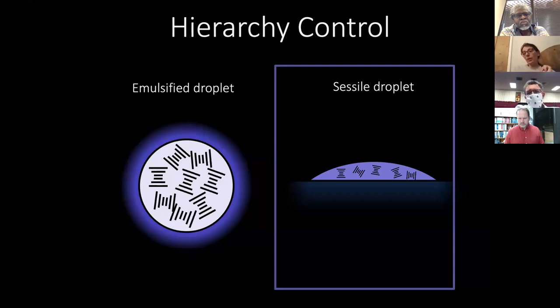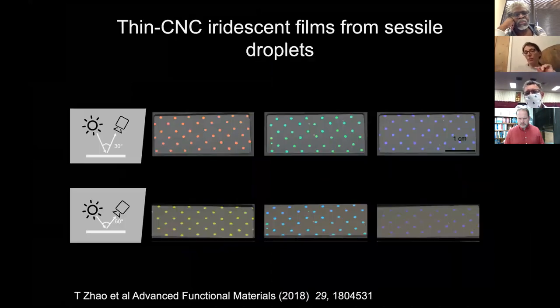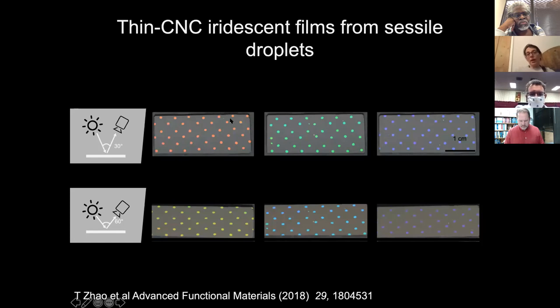And this is completely different if you have a sessile droplet, if you have a mini film. In fact, here, as you can see, we can print again in different colors, but now when you print, since you don't have a hierarchical structure, it is different: when you look at it from a different angle, the color looks completely different.